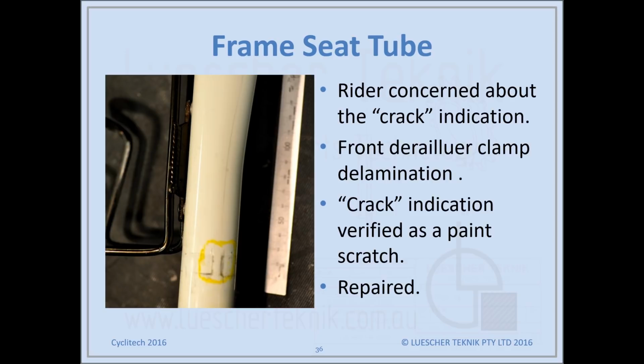Now this is a really interesting one, because originally the customer brought the bike in because he was concerned about this long indication through here, and so I took the front derailleur clamp off to scan it to get better access. The original crack indication was just a deep paint scratch, and there was no underlying structural damage. However, the scan found that the front derailleur clamp had been over tightened, and as you can see, this area marked in yellow had quite a large delamination. So that was repaired, and then we repainted and did the paint repair on that other area at the same time.